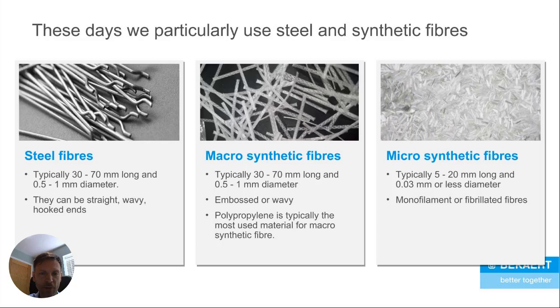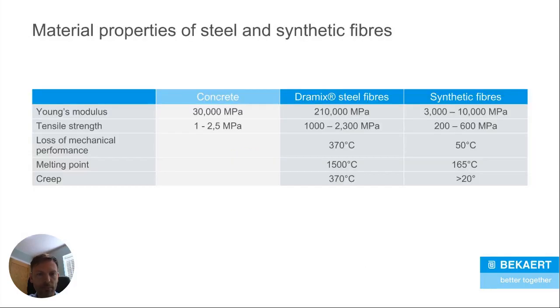But after the first 24 hours after concrete has been cast, those fibers stop doing their work. They don't add long-term ductility to the concrete. They don't replace steel. It's important to note. What's also important to note is, though, that they can be used in combination with steel mesh or steel fibers because they do a different job. The other type of plastic fiber on the market are macrosynthetic fibers, which are effectively plastic fibers that try to copy the shape and size of steel fibers.